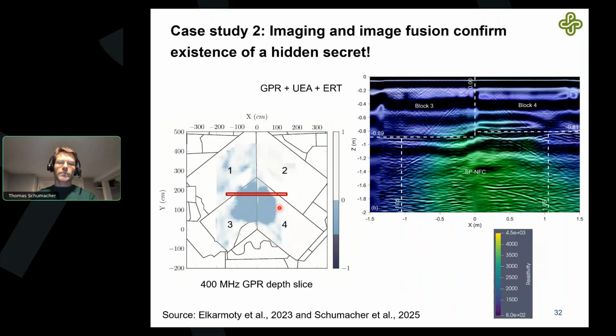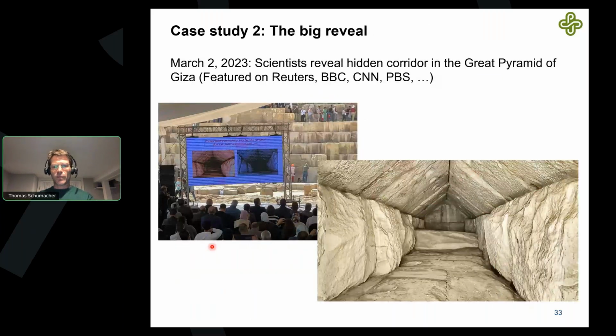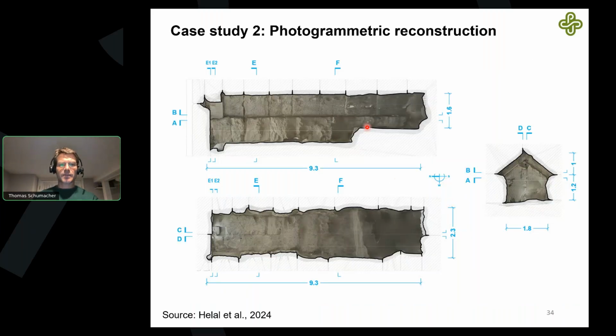So we were basically able to show that in this horizontal cross section, there are the blocks that we can see, blocks 3 and 4, and behind it might be a big air volume. And that's what was revealed in March 23. They were able to push a teeny little camera from below into this, and that's what they found. So we found this cross section, about a 9-meter long tunnel. That was a big reveal. Since then, researchers have created photogrammetric reconstructions of the tunnel, giving you a better sense of what it looks like.